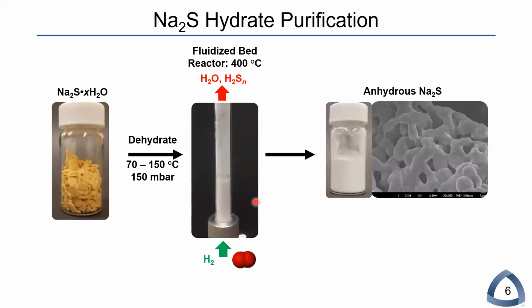This material can then be purified further by reacting with hydrogen gas at 400 degrees Celsius. And in the process, the hydrogen reacts with the solid oxygen and sulfur species to form H2O and H2S gases, which self-separate from the reactor bed. The result is a high purity form of anhydrous sodium sulfide, and you can note the stark contrast between the initial and final product.